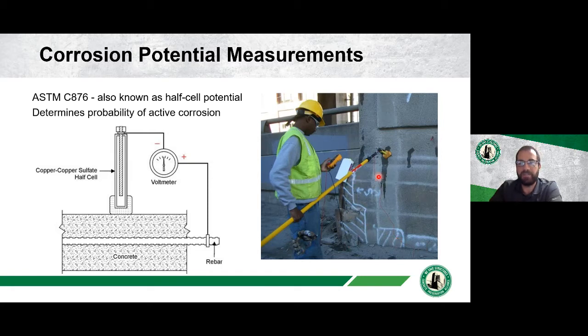So if we do half cell beyond these areas of current physical damage, we will know where corrosion is active beyond those. Obviously the white hatched out areas are areas where there's physical damage, but we also want to know where corrosion is active beyond that. Because if we don't repair those areas, then in a few years, they're going to have more delaminations and spalls in those areas that will have to be fixed.